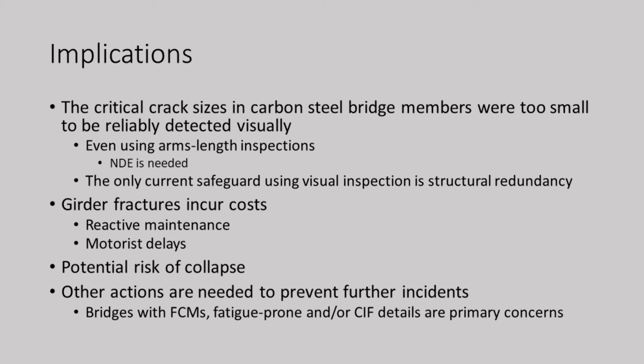The Hoan Bridge was a 3-girder bridge. It came close. It had 2 complete girder fractures, and the 3rd girder had a crack 30 inches long in the web. Somebody saw that right when the deck started to sag, and they closed the bridge immediately because they were a state trooper. There is a case in Australia where a 4-girder bridge collapsed 15 months after it was opened, and it had the same structural detail at the same location across the bridge, and they failed in cascading order. But it's kind of an outlier for a number of reasons.